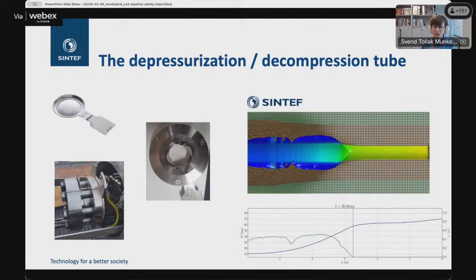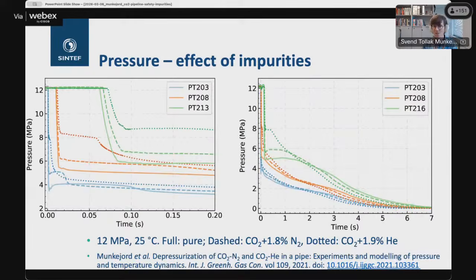Now, at the one end of the tube, there is a flange like this, and we attach a rupture disc, which is fabricated and calibrated to rupture at a given pressure. So for the experiment, we slowly and carefully raise the pressure inside the pipe to a given pressure. The rupture disc ruptures, and then we take the data, what happens when the pressure wave travels upstream. Doing that, we can make plots like this, and I'll try to explain.